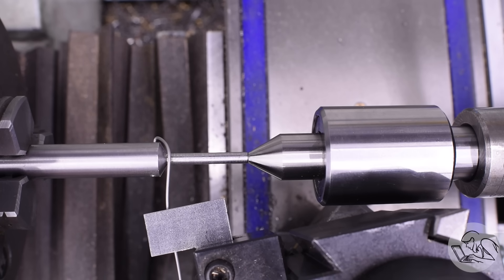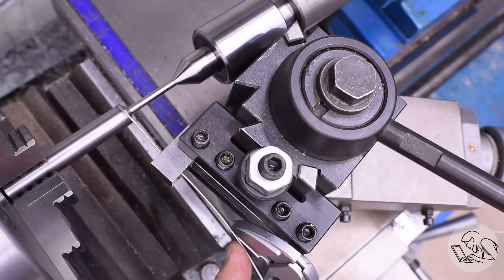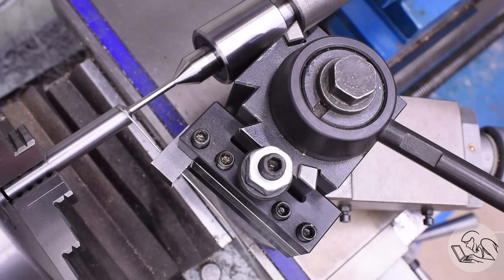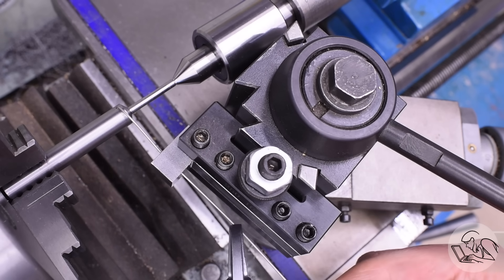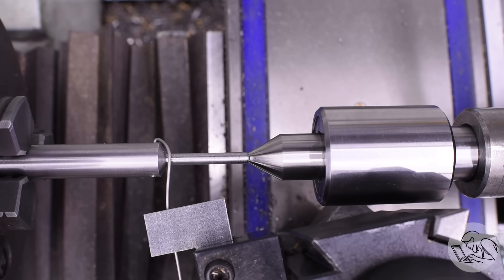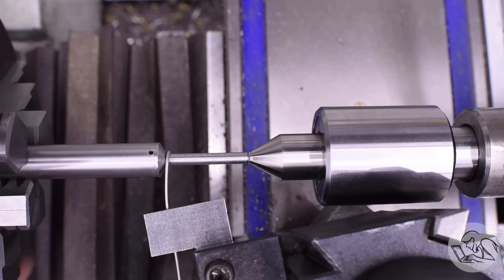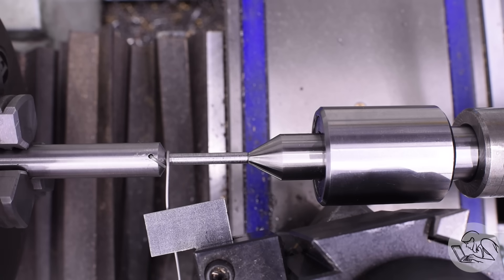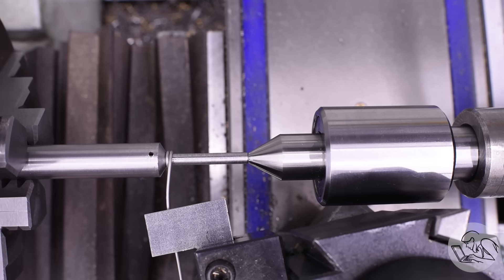Now it's time for some tension. I find it easiest to do this with smooth jaw pliers. Do not try to do this with your hand. You won't be able to hold it tight enough and if you're going to be doing this under power that's a really good way to lose a finger. With tension on I'm going to wind the chuck by hand and put a couple of wraps of closed coil at the end. You want a couple of wraps of closed coil at each end of a compression spring, or if you're doing a tension spring then all the coils are closed. As I'm doing these I'm also moving the carriage forward a little bit by hand just to keep the closed coils from piling up on each other. You want a couple of extra wraps at the leading edge of the spring because that end gets distorted when you pull it off the mandrel.